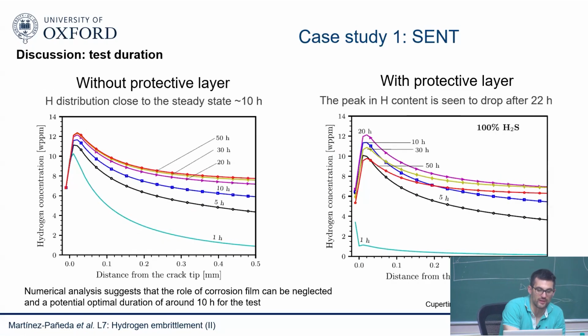So first we did some simulations of crack tip stress fields and hydrogen concentrations, and we wanted to know what happens in terms of hydrogen diffusion in these materials, how quickly you get a steady state, how quickly you get the peak hydrogen concentration. And you see the simulations here, so this is without any crack growth, and you see that more or less, the steady state, maybe you need 50 hours, but after 10 hours, your hydrogen concentration is almost there. So really, the hydrogen distribution is very close to the steady state after roughly 10 hours.